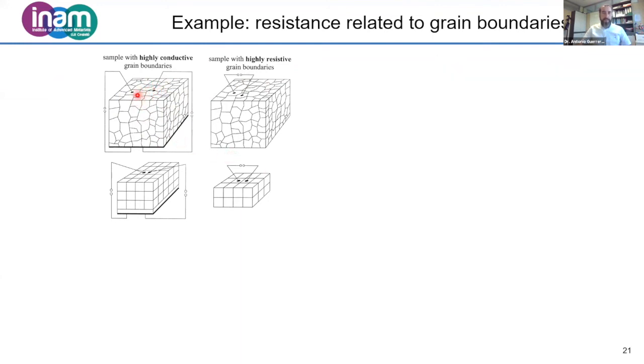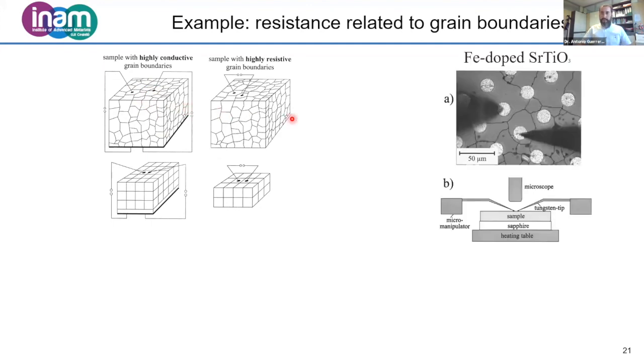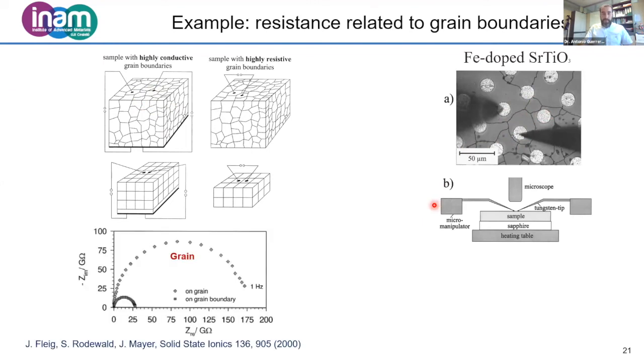Okay, so we have a polycrystalline material. We want to know how conductive our grains are. So we go to the lab and design one experiment. For example, we can deposit microcontacts at different sides of our grain, or we can place contacts on top of the grains. For example, in this contact here and this contact here, if this grain is very conductive, the conductivity could go through the grain, okay? And then we do the measurements.